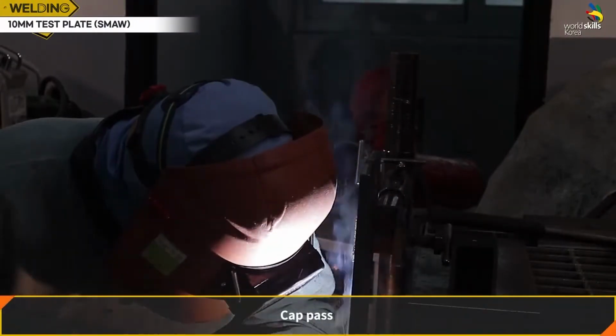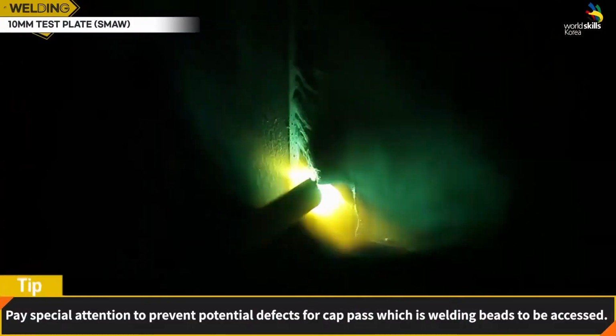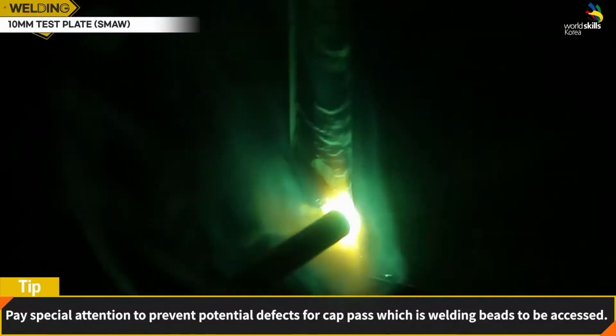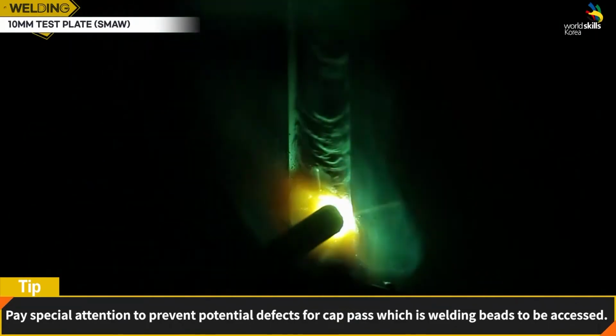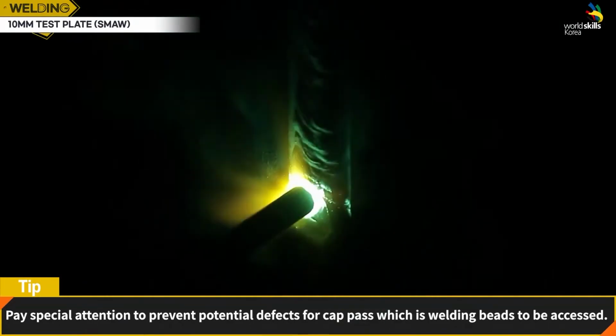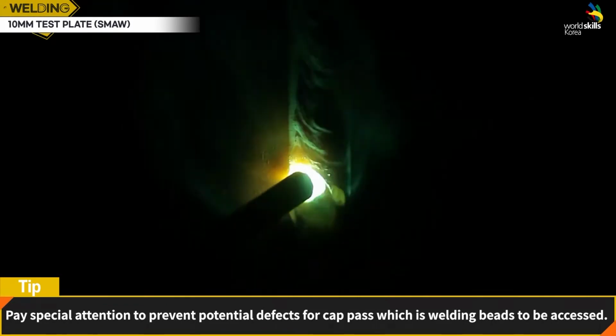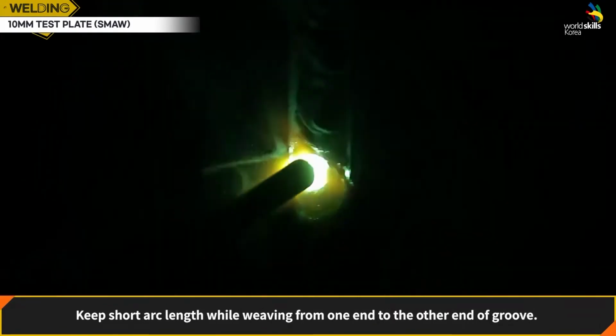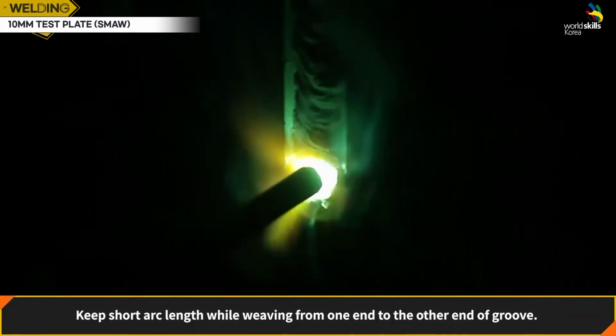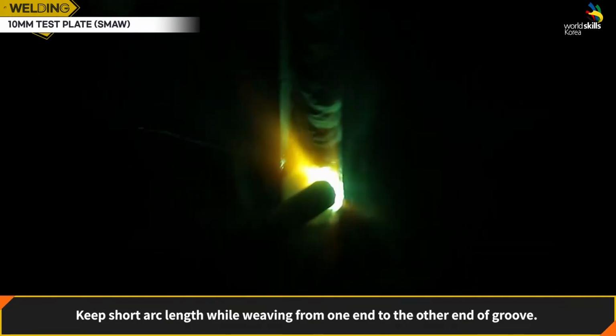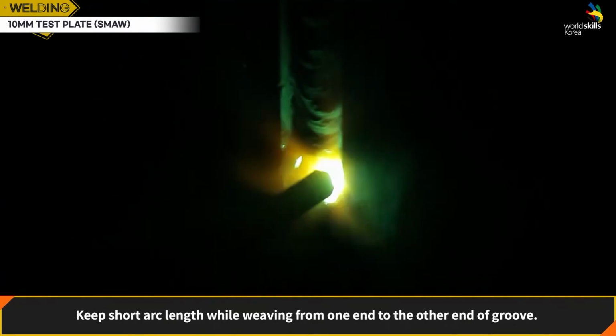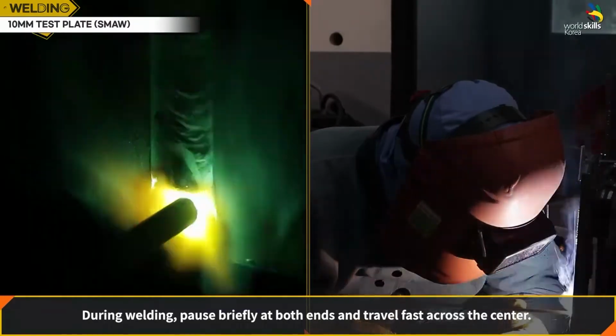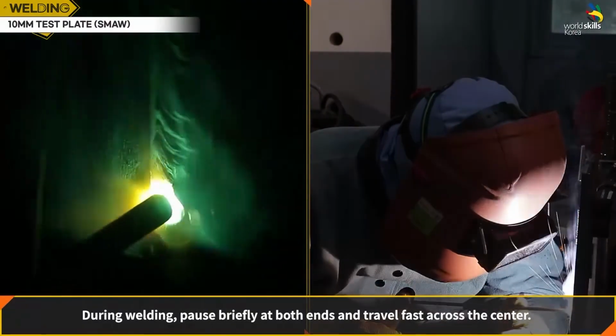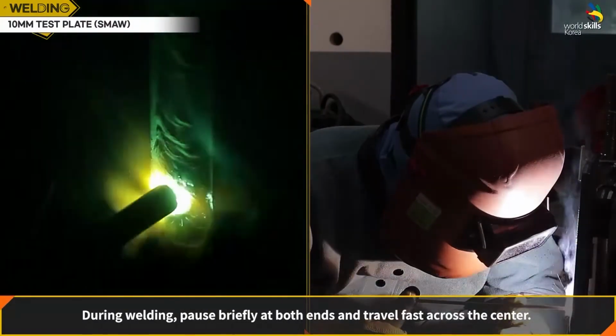Base material cap pass. Pay special attention to prevent potential defects for the cap pass, which is where the welding beads are exposed. Keep a short arc length while weaving from one end to the other end of the groove. During welding, pause briefly at both ends and travel fast across the center.